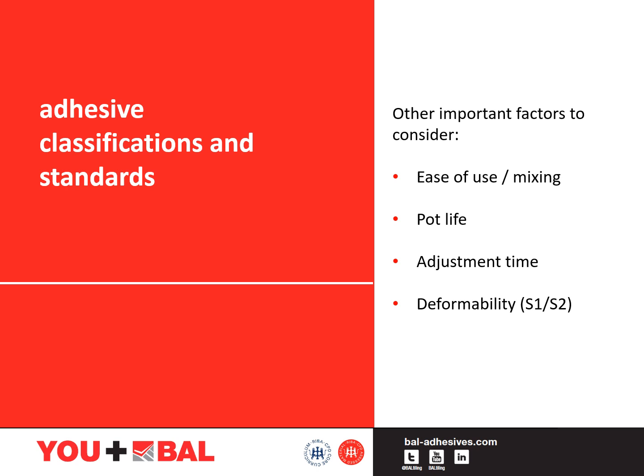Other factors may include examples such as fixing a large format tile, which means an adhesive with prolonged pot life and working time is usually important. Pot life, for instance, is the time a product has once mixed to use. Standard setting products may last up to 5 hours, whereas rapids may be as little as 30 minutes. The adjustment or open time is the time a product has once applied to the background.